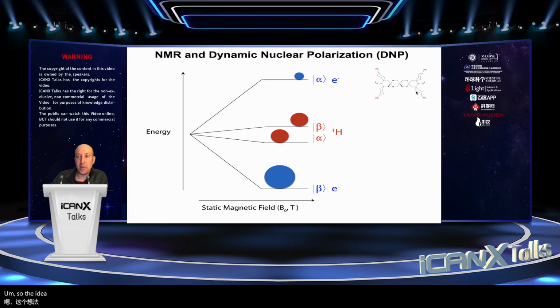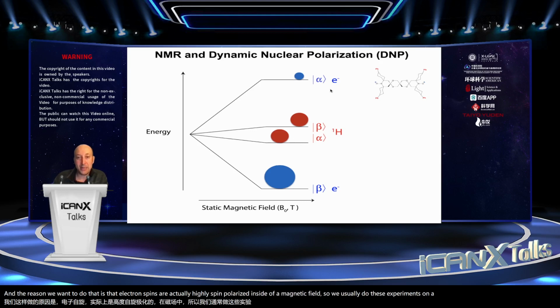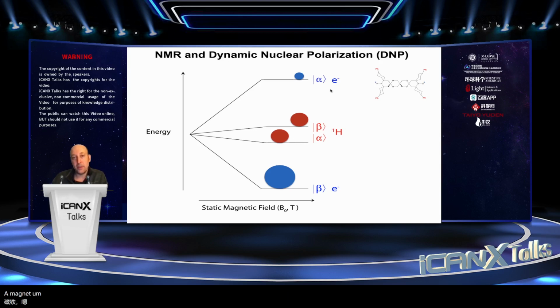So the idea behind a DNP experiment is we're going to dope our samples with stable free radicals. The reason we want to do that is that electron spins are actually highly spin polarized inside of a magnetic field. So we usually do these experiments on a 9.4 Tesla magnet and at a sample temperature of around 100 Kelvin. Under those conditions, the electron spins are going to be about 6% polarized.